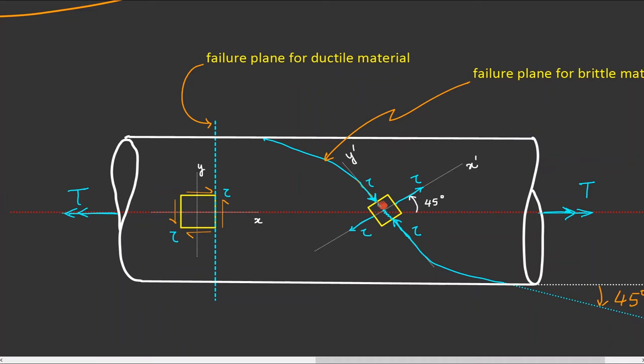As a consequence of the tensile stresses pulling the element apart along axis Y', the element is subjected to a potential crack, and tracing the path of this crack shows it follows the path of a helix. In a shaft subjected to pure torque, the path of failure could be helical, with the helix making an angle of 45 degrees with the shaft axis. If the shear strength of the shaft material is lower than its tensile strength, failure occurs by shear, and the failure is a shear cut at the critical section — this is the failure plane for ductile materials.